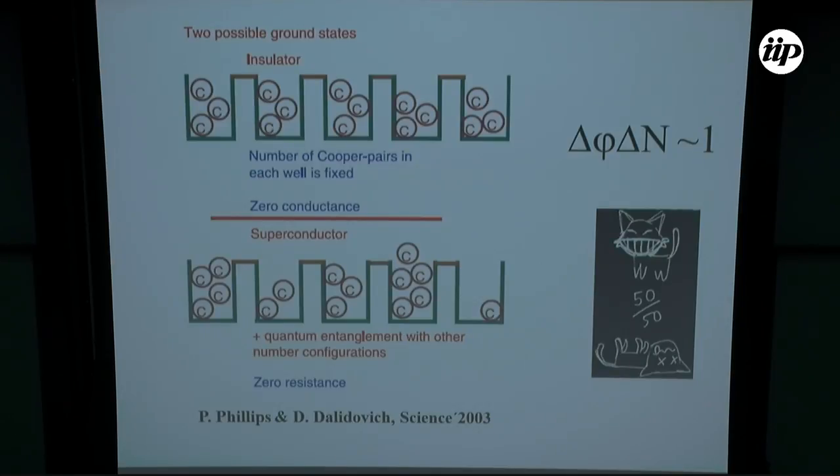In other words, you have 100% certainty that you will find all the Cooper pairs localized within the grains. You have infinite uncertainty in the phase. In other words, you have the superfluidity of vortices. And just the opposite, when you have this possibility, the Cooper pairs transfer, and you just have, for instance, pinning localization of the vortices, you have the zero resistance state.